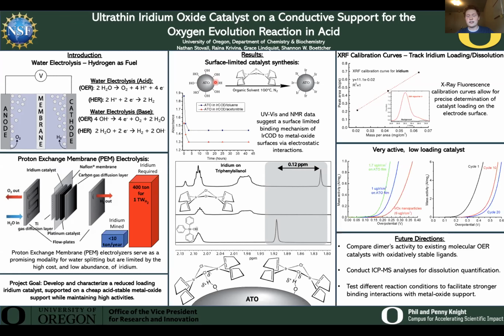We did a further investigation using nuclear magnetic resonance spectroscopy, where we used a model metal oxide, triphenylsilanol, that is suitable for NMR, and we tracked this hydroxyl hydrogen before and after reacting with the iridium dimer. Before, this peak here corresponds to the hydroxyl hydrogen. In the middle, we have the iridium cod NMR, which has no hydrogen peak, as you'd expect. After adhering the iridium to the triphenylsilanol, we see a slight shift in this hydrogen, but we do not see its disappearance. This suggests that quite likely our iridium dimer is adhering to the surface of our metal oxide instead of forming a direct bond, possibly through the partial positive hydrogen of the metal oxide hydroxyl group and the partial negative chlorines in our iridium dimer.